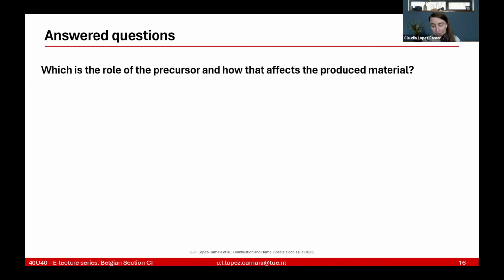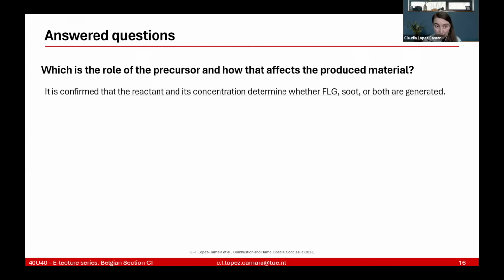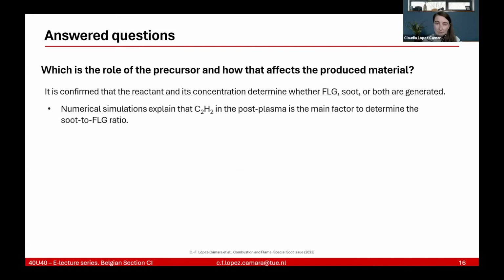And therefore, we did achieve our answers. So to which role is of the precursor and how that affects the produced material, we confirmed that the reactant and its concentration determine whether few layer graphene, soot, or both are generated. And even though I did not show it here, we also have numerical simulations that explained that C2H2 in the post-plasma region is the main factor to determine the ratio between the soot and few layer graphene.